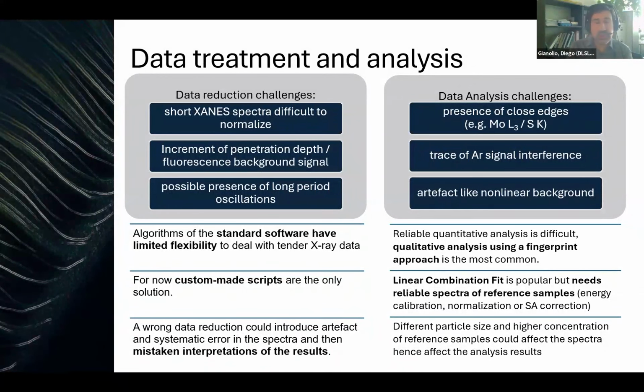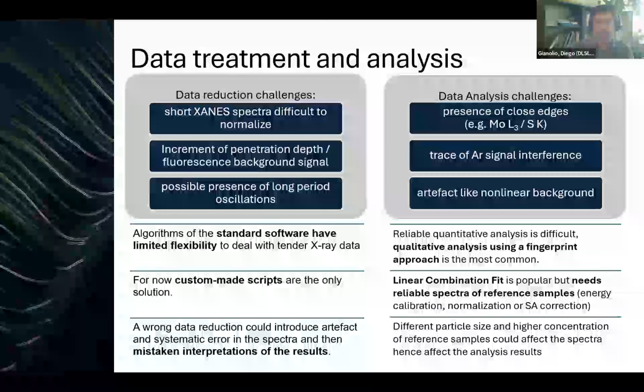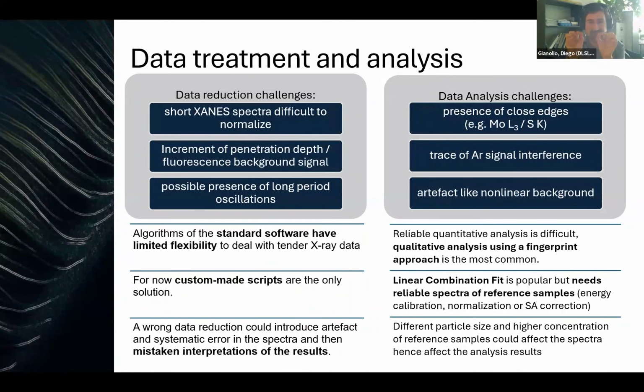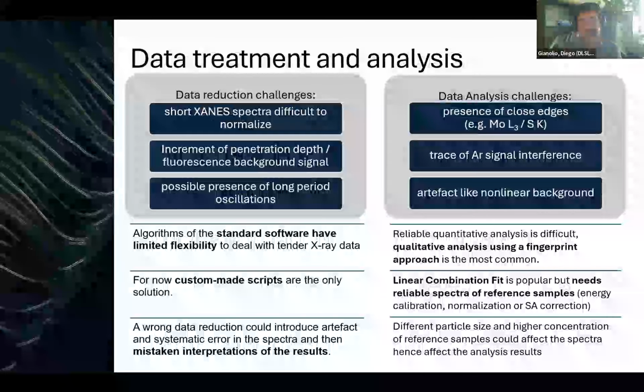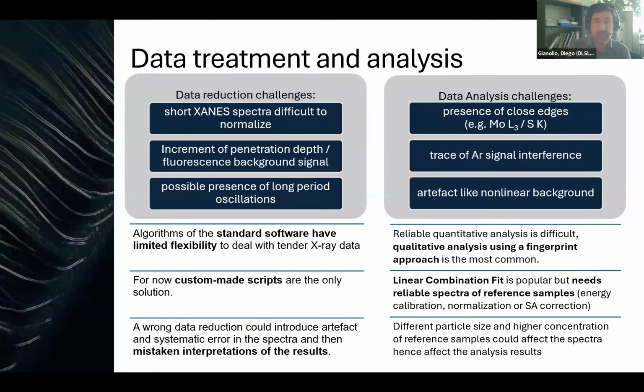So in this case, it is possible to do the analysis with the common tools like Athena and Larch, but having a very short range, sometimes people need to spend a lot of time picking the points for the pre-edge and post-edge so that the lines are well aligned. And many people that are working with tender X-rays tend to develop their own custom-made scripts in order to have a normalization that is adapted to the signals that they collected. Of course, as for any other data analysis, if any error is made during the data reduction, this could introduce artifacts and systematic errors and then lead to a mistaken interpretation of the results. So it's very important to be able to do this properly and to provide the right tools to the community of users.